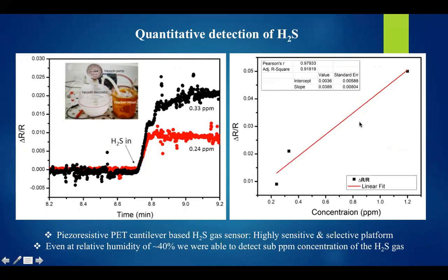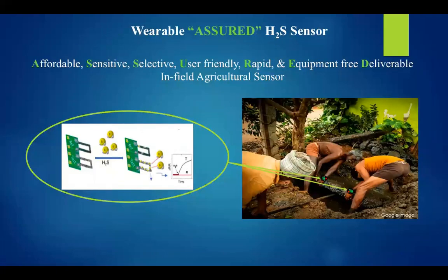When we extrapolated the amount of H2S in the ambient experiment, we found that the concentration in the low concentration scenario of the experiment was lower than 1 ppm. We can say that this platform is also quite selective because in presence of over 40% humidity, we could still sense H2S. So with this preliminary data, we are sure that we'll be able to get a reliable, assured H2S sensor.